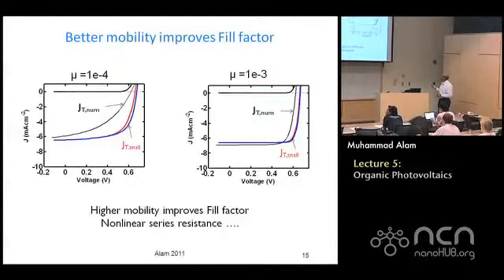And that is indeed the case, because if you do the numerical simulation with just a little bit higher mobility, this mobility is 10 to the power minus 4, this mobility is 10 to the power minus 3, you can see it immediately approaches the analytical solution because the approximations are now better. See how low the mobility is. The silicon mobility would be hundreds of times or 1,000 times more than this, right? Look at this, 10 to the power minus 3, 10 to the power minus 4. Cheap material has low mobility. So that is expected.